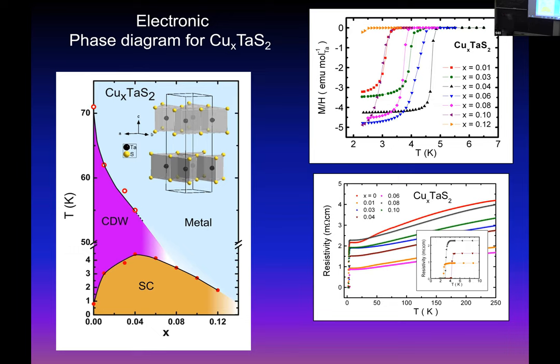Take something like TaS2, a known charge density wave material, and you change the electron count by putting copper between the layers. It's a layered dichalcogenide, so the electrons are confined to be in layers. Then if you put copper in between the layers, you get the copper to give up its charge. The copper donates an electron to the tantalum disulfide layer.